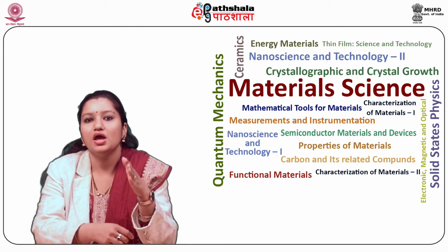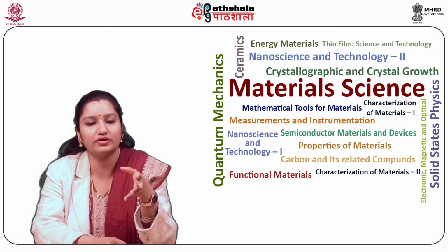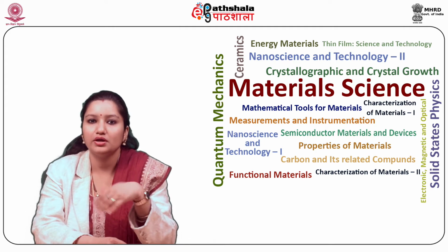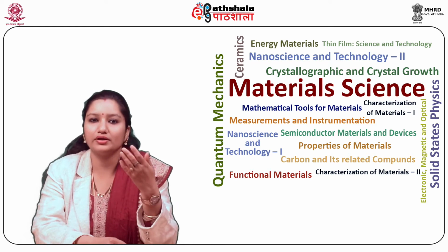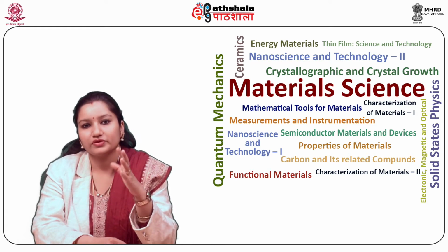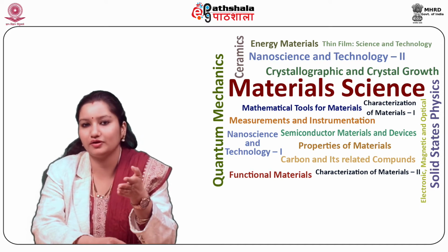When electrons are accelerated up to high energy levels, that is a few hundreds of kiloelectron volts, and focused on a material, they can scatter or backscatter elastically or inelastically to produce many interactions, sources of different signals such as X-rays, Auger electrons or light.